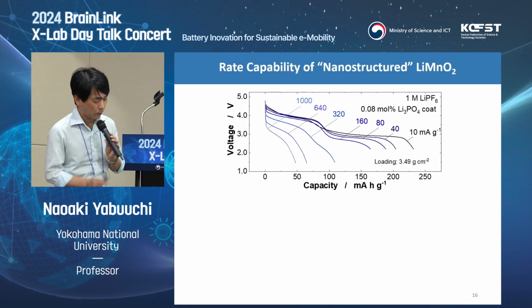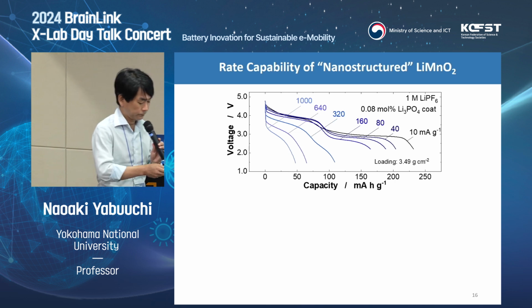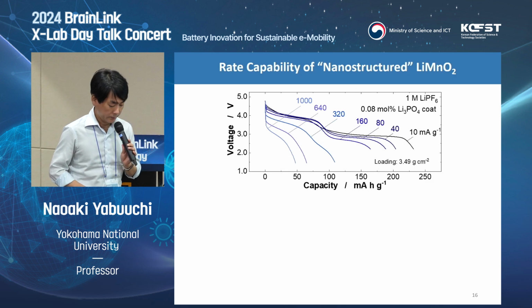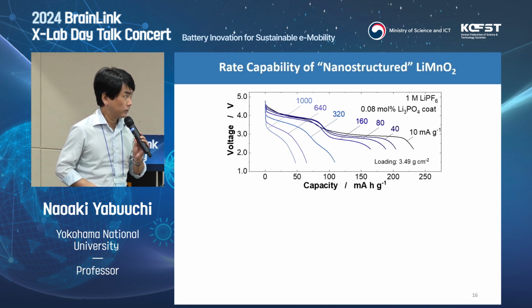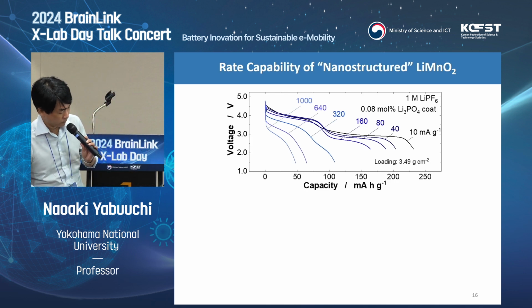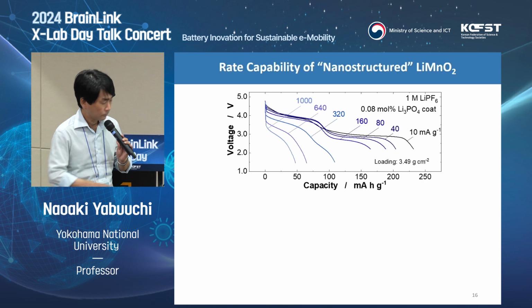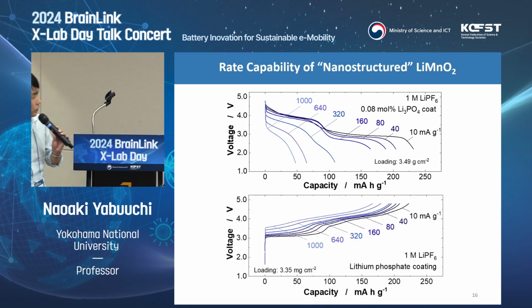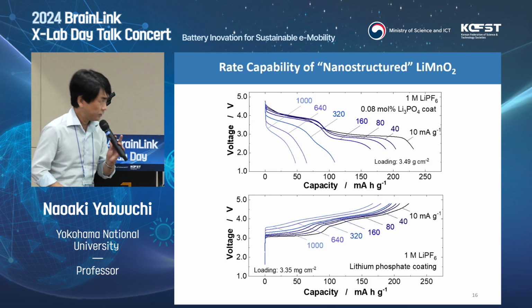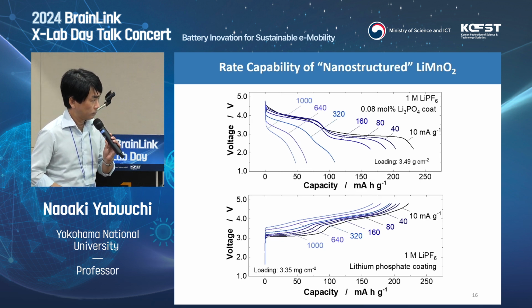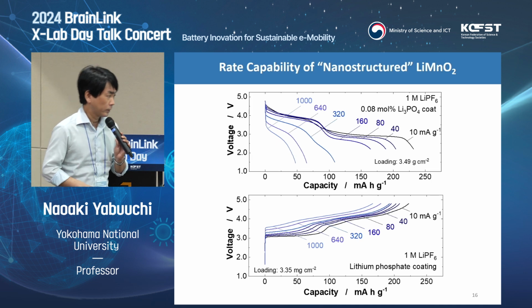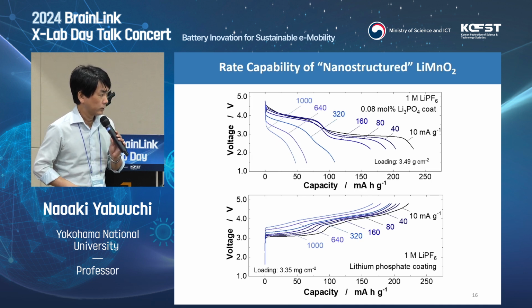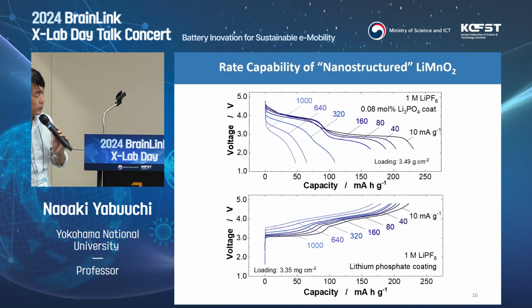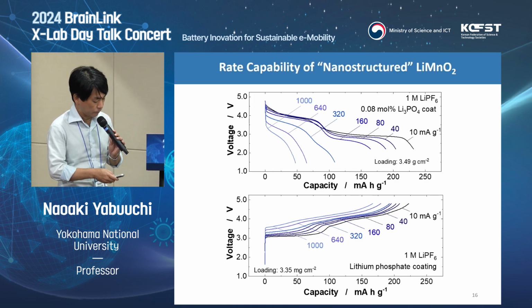And also the only problem for the pure manganese system is that discharge rate capability is so hopeless. Even at 320 milliampere per gram, we are losing nearly 40%, nearly 60% of our discharge capacities. However, the good news is charge rate capability is so nice. Discharge rate capability is not good, but charge rate capability is so amazing. Even at 1000 milliampere per gram, this sample shows very good charge rate capability. So of course, for electric vehicle applications, the most important character is quick charge ability. Therefore, possibly this sample can be used for practical electric vehicle applications in the future.